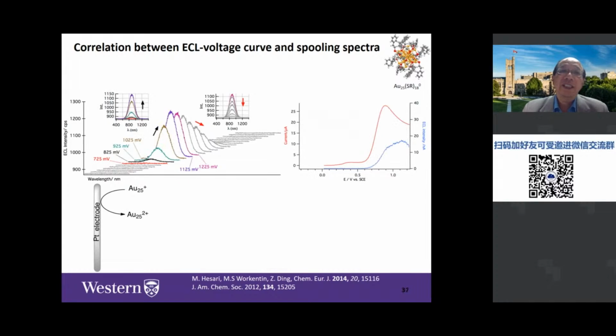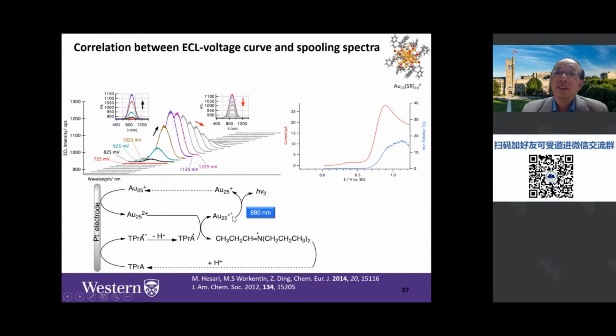And then we just continue the scanning. That means when you apply the higher voltage, then you can continue to oxidize the gold 25 plus to gold 25 2 plus. And the same thing, TPrA still gets oxidized to the TPrA radical cation, and then deprotonates to get TPrA radical. And then this gold 25 2 plus reacts with TPrA radical, and then gives you gold 25 plus excited state. And this should give the peak wavelength at 880 nanometers.